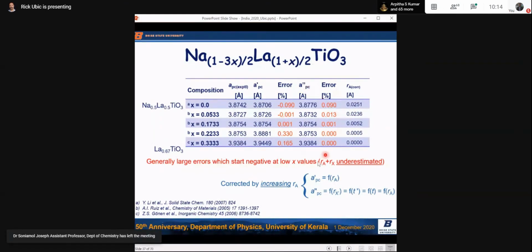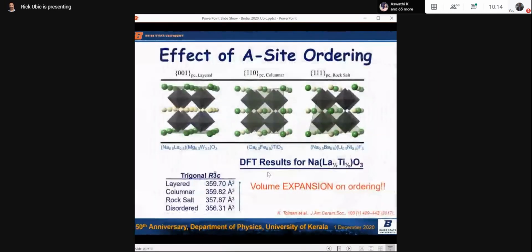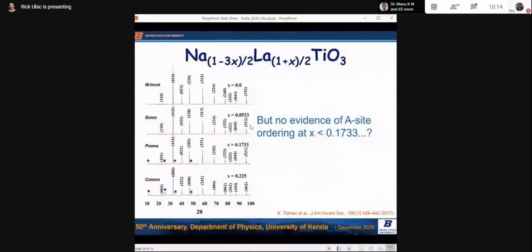So this was the peculiar thing that we saw about the ordering. I didn't even know what to call this to start with, because ordering was causing an expansion of a cation size. And that didn't make sense to me to start with. Why would you have a volume expansion on ordering? It's not what we saw on the B site. But we did DFT, and however you model these in a tetragonal or a trigonal structure, you always get the disordered form has a smaller volume than any of the ordered forms you can do, either laying on 001 or 110 or 111 layers. Perovskites are known to layer in all of these ways. The A site normally this way, but not always. No matter what you did, you always got that ordering caused a volume expansion. So this is a real effect. We did work it out later. I'm not sure I'll have time to explain it today.